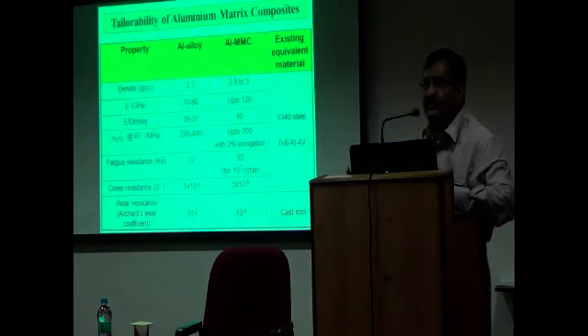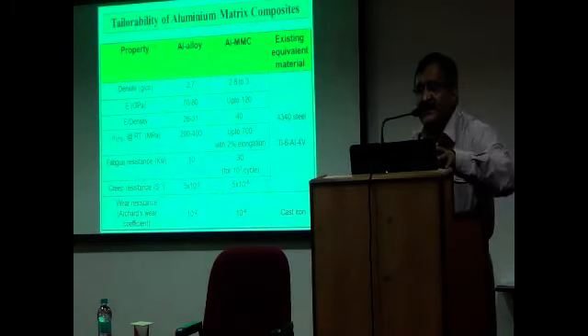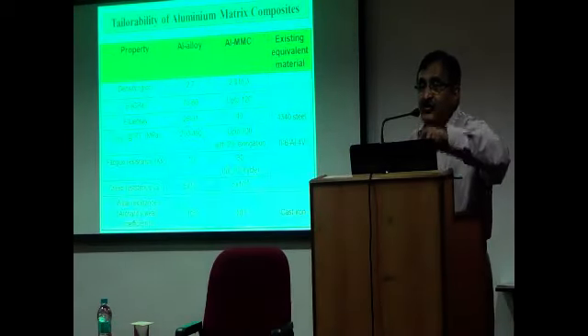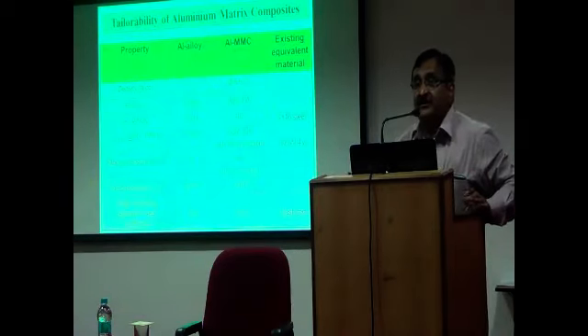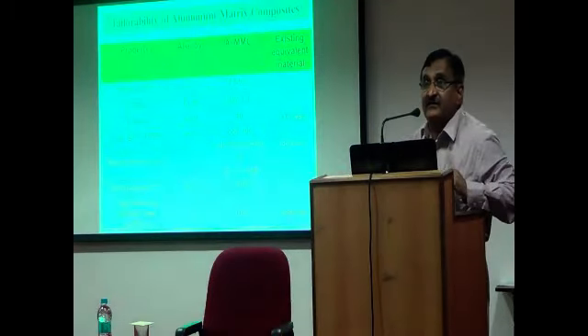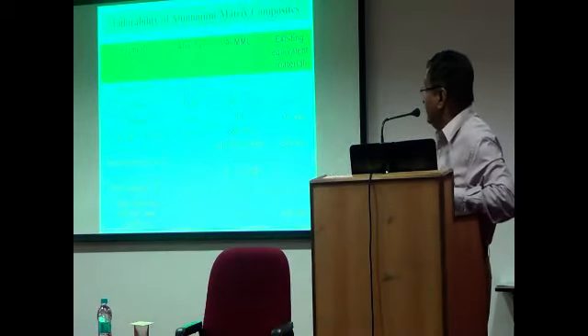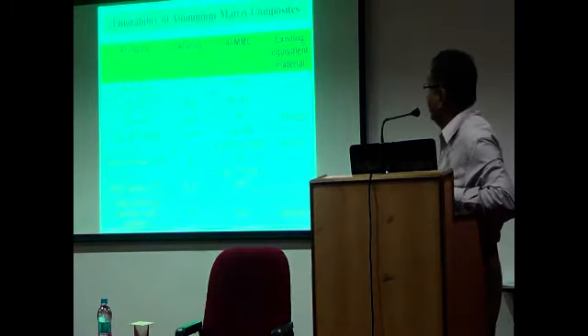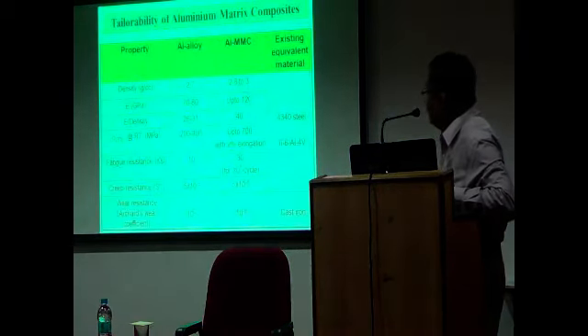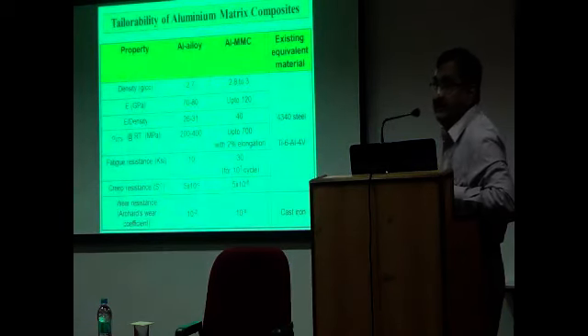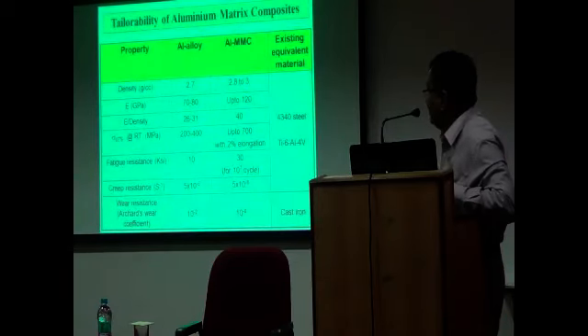Now, I'd like to tell you how, by compositing aluminum with this reinforcement, you can translate aluminum into a steel, into a titanium, or into a cast iron in a variety of applications. If you look at the density, aluminum is 2.7, and when you composite with this, you can get about 2.8 to 3. What is most important is the elastic modulus, the stiffness, the specific elastic modulus, and the UTS, the ultimate tensile strength, at room temperature.